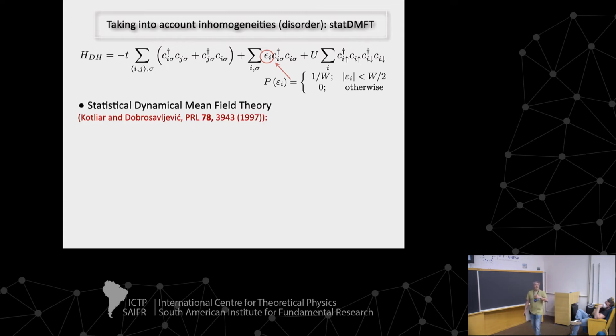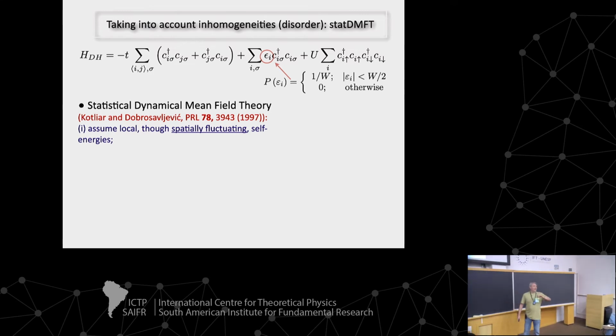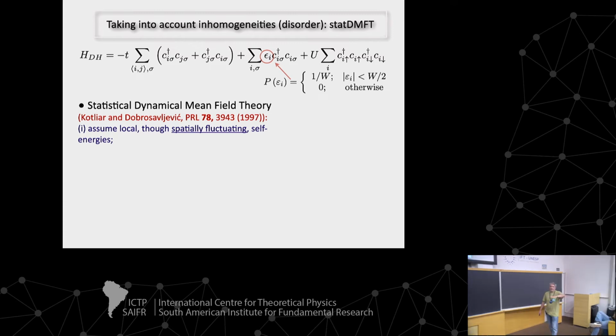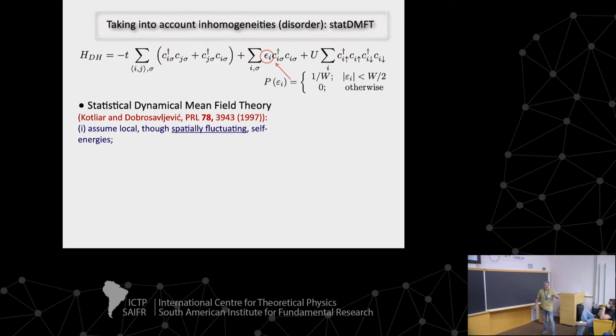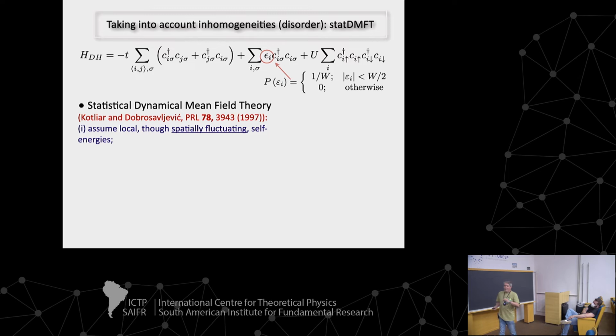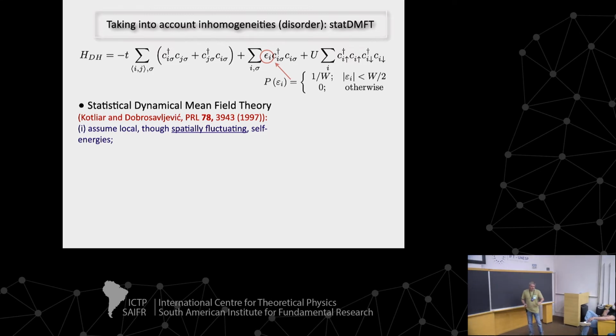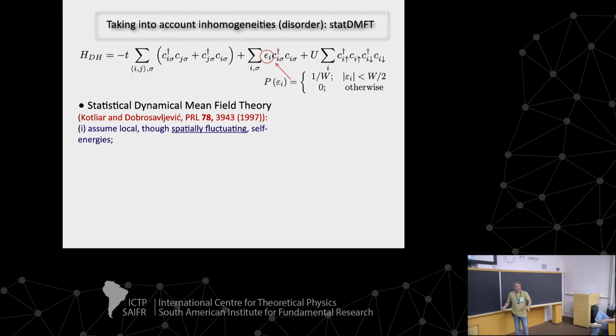So now you can do an extension of dynamical mean field theory to incorporate disorder. This has come to be known as statistical dynamical mean field theory, but the spirit is the same. So once again, you assume local self-energies. First of all, there's no K anymore. The system is not translationally invariant, so you have to look on the basis of sites. And you also assume that the self-energy is local, but now it can fluctuate because of disorder. So on one side the self-energy is one thing, and on the other side the self-energy is something else, because they're going to be different. It's a disordered matrix.